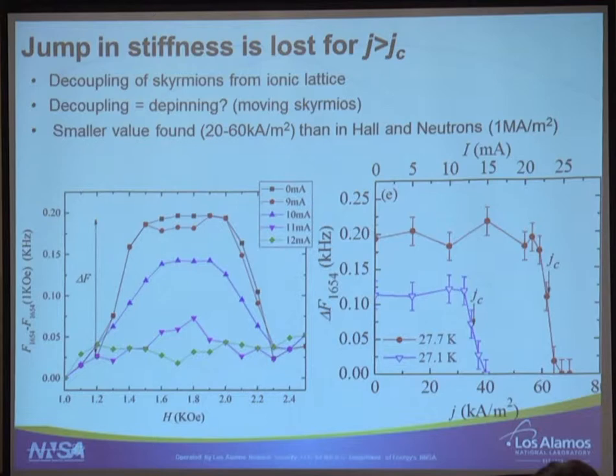So we see 2 things. One, we can erase the stiffening. The coupling between the skyrmions and the lattice can be erased by current. The other thing is that it depends on temperature. It depends on where you are in your skyrmion lattice, you will have different values.